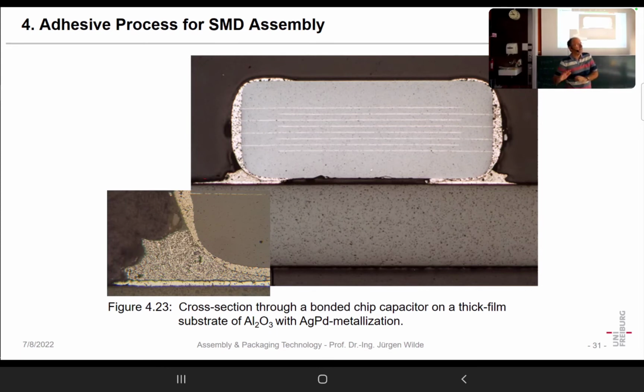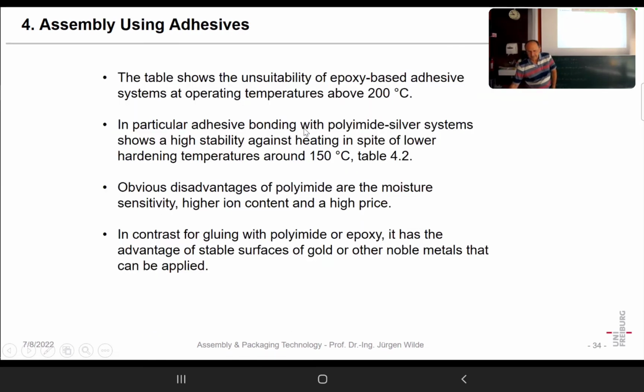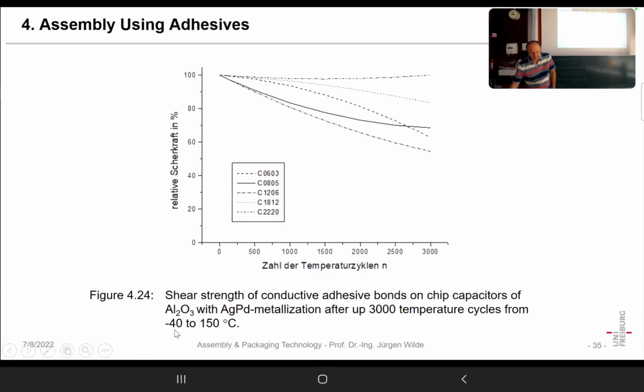My successor later on did the same work up to 175, and we built these and we put them in temperature cycles. Here it's temperature cycles -40 to 150. So all of the parts are put in a chamber, and in the chamber we have on top a hot compartment and we have a cold compartment on the bottom. The cold one is maybe minus 40 degrees centigrade, the top one, for instance, 150. And then the specimens are on a lift and they are brought down, up and down, and always kept for 15 minutes or 30 minutes.